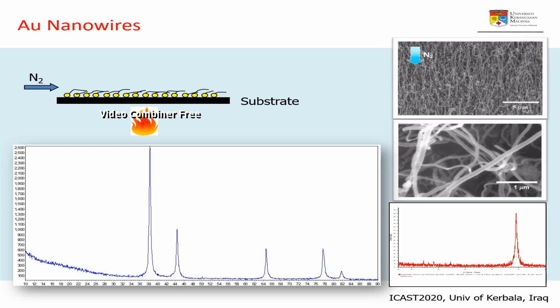However, when we changed our measurement strategy from conventional powder X-ray diffraction to detector scan, a completely different diffractogram was observed. With right measurement planning, the observed diffractogram was successfully matched with the standard reference pattern for gold. Hence, it was confirmed that the nanowires are indeed gold nanowires.